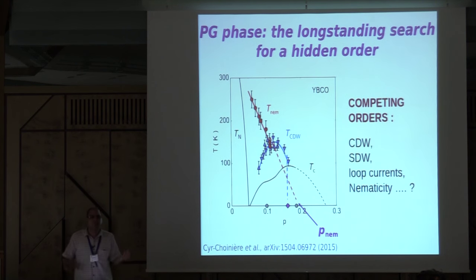Most of the time, this is the vision that people working in this field give you. And people have been looking desperately for this not well-identified order. It's a nice achievement of these recent years that they have found charge density wave under application of magnetic field. Now, if there is no magnetic field, the charge density wave state that you see here is perhaps not stable. It's a short range density wave, or so on. But it looks like a really important phase and seems present in all the cuprates family.